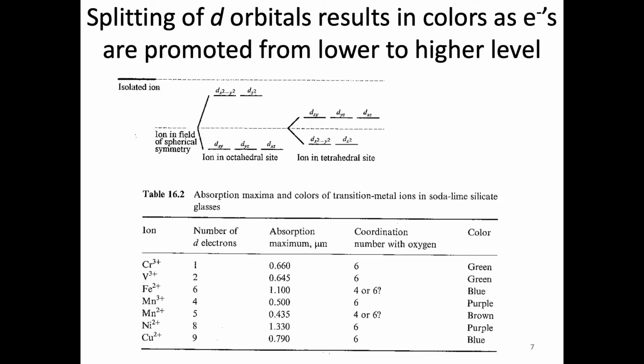And so this is going to be looking at what happens in these coordination sites. What we're going to see is that the d orbitals, those orbitals that can hold 10 electrons and have five orbitals, instead of all of those existing at the same energy state, which would be the case in spherical, some orbitals lower in energy and some raise in energy. The y-axis here is basically an arbitrary, relative energy. So we're going to see what we call splitting of the d orbital. And this is what tells us about those electron transitions and tells us if there's going to be coloration.